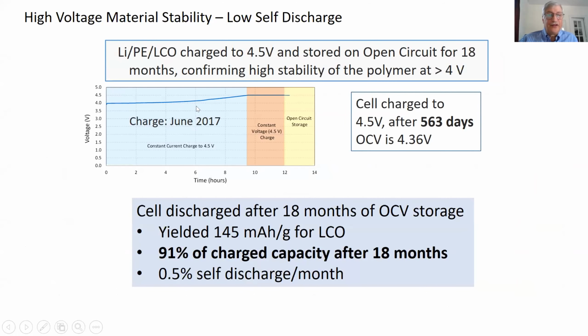Just to show you that you've got to have more than ionic conductivity. This is a lithium metal, not a lithium ion, lithium metal battery made with lithium cobalt oxide. And it was charged in June 2017. And a year and a half later, it retains 91% of its capacity after 18 months. And that's as good or better than the best commercial lithium ion battery. So there's really no appreciable self-discharge. So this thing has an excellent shelf life, stability at above 4 volts.